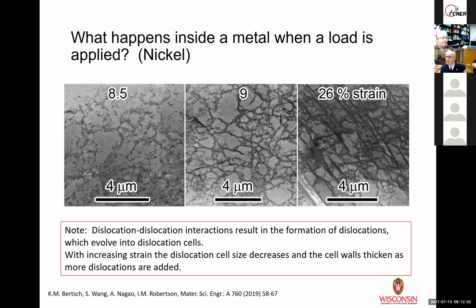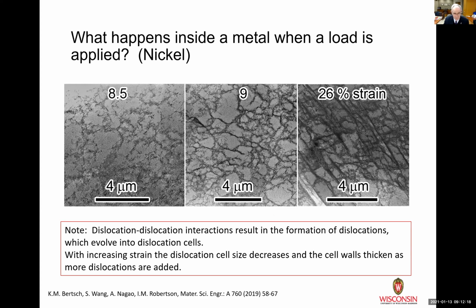What happens to the dislocation structures that you see? So here's just an example. It happens to be nickel. The numbers that you see, the 8.5, the 9, and the 26, tell you the percentage of plastic strain that this material has been subjected to. You're not looking at individual dislocations now, but you're looking at collections of dislocations. And you'll notice again you'll see this collection of dislocations here.